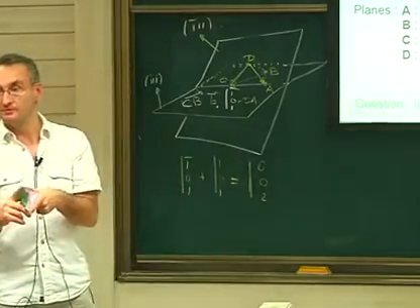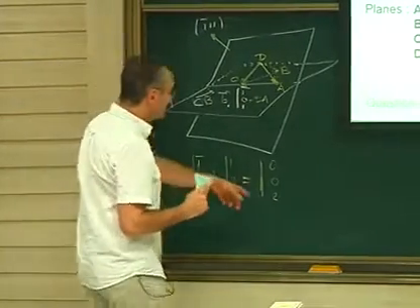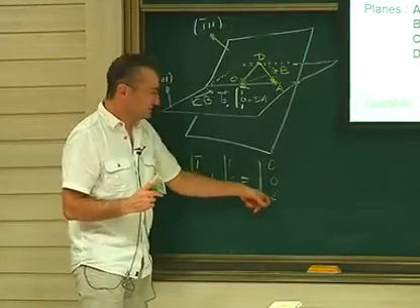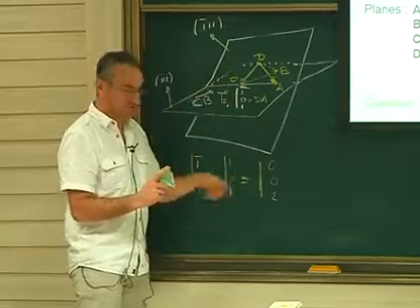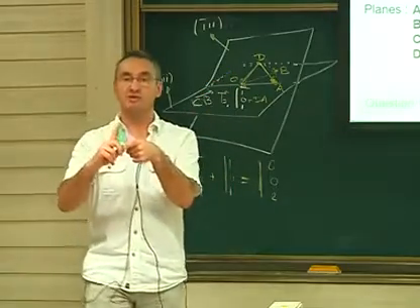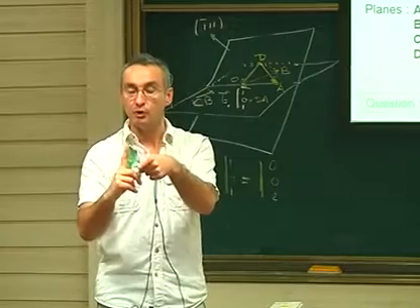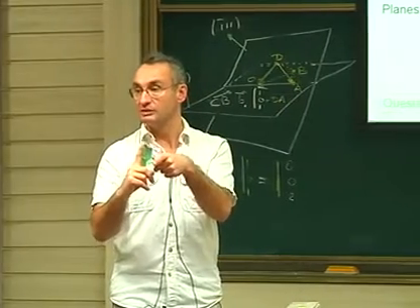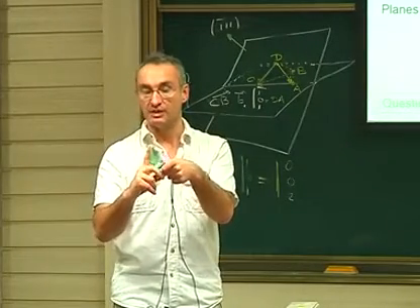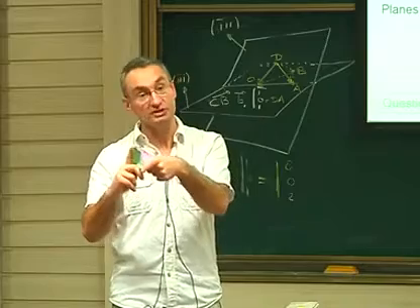So it's a specific one. It's something which is sessile. You see, it looks like sessile. It's not in any of the two planes, the resulting intersection. But the interaction is, and we'll see later on, weak because of the interaction of orthogonal vectors. The stress field will be weaker than the Lomer-Cottrell typically. So it's a weak junction, but it is a junction.